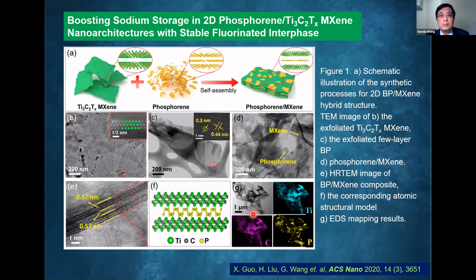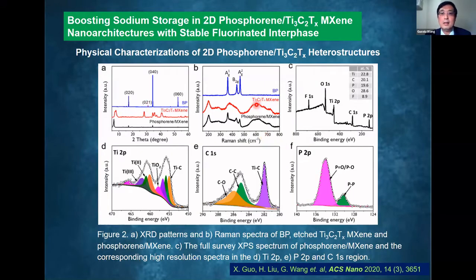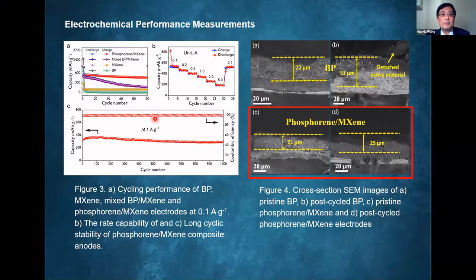And this is our recent work. We try to boost the sodium storage capability of MXene nanosheets. We add in phosphorene. Phosphorene is another kind of 2D material, and because phosphorus has a very high theoretical sodium ion storage capacity. So this SEM confirmed we homogeneously distribute small phosphorene nanosheets on the surface of MXene nanosheets. MXene nanosheets are large in size. And then we did characterization, XRD and XPS. And then we test the electrochemical performance. You can see we can boost the sodium storage capacity to almost 600 milliampere-hour per gram.